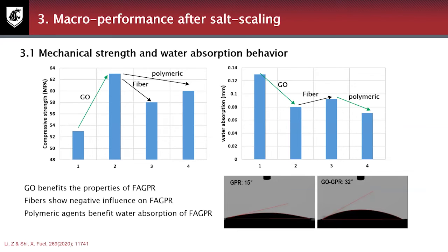From these figures, we can see that after adding graphene oxide, the strength of concrete increased from 53 to 63. But after adding fibers and the polymeric agent, the strength decreased a little bit, especially for the fiber one. But this is a common issue in fiber reinforced composite. We also tested water absorption, and we found that after adding graphene oxide, the water absorption decreased, and then after adding polymeric agents, the water absorption continued to decrease. Based on this result, we briefly summarize that GO benefits the strength of geopolymer concrete, and the polymeric agents benefit the water absorption of geopolymer concrete, but the fiber seems to show a negative influence.